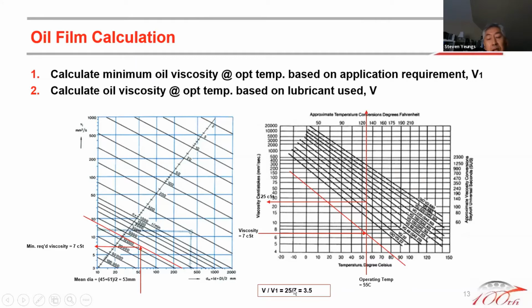As I mentioned earlier, under the oil film parameters, in that little green box, I'm looking for somewhere between 1 to 4. That would optimize my selection. So in this case, 3.5, I think is very good because the lubricant is not an overkill as far as the viscosity is concerned. That's why the temperature was able to be maintained at 55. So from that perspective, the selection was quite adequate from the oil film standpoint.